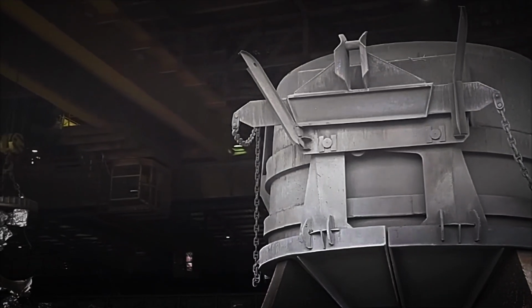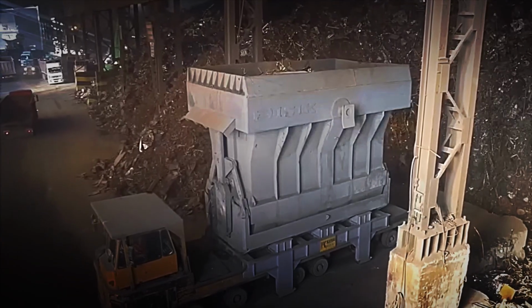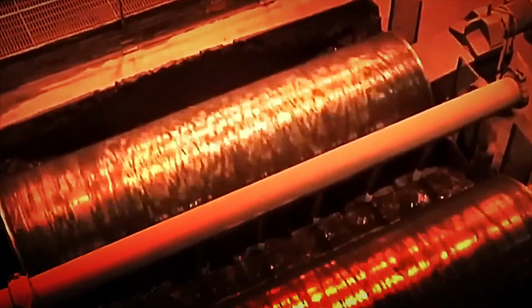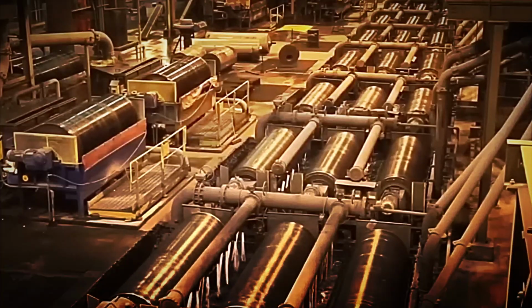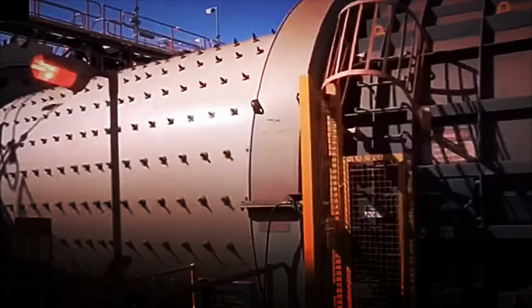In pelletizing plants, the ore is mixed with water, binders such as bentonite, and fluxes such as limestone. This wet mixture is introduced into rotating discs or drums, which, as they rotate, compact the material into small balls. Although they may seem simple, pellets are key to the efficient operation of the smelting process. Once formed, they pass through special furnaces where they are heated to temperatures close to 1,300 degrees Celsius. The heat gives them strength and a porous internal structure that facilitates air circulation in the furnace.